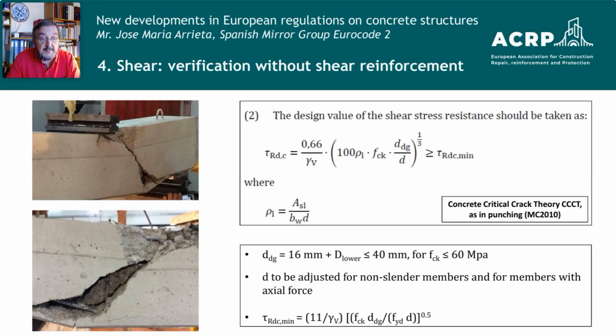Then finally, my third issue is the shear. First, I'd like to say that in the European Subcommittee we have preferred physical models over empirical models, and then in shear and punching we use two physical models, one for structures without shear reinforcement, and the other for structures with shear reinforcement. Both are based on Model Code 2010, and the first one here corresponds to the critical crack theory, which is applied to obtain the expression.